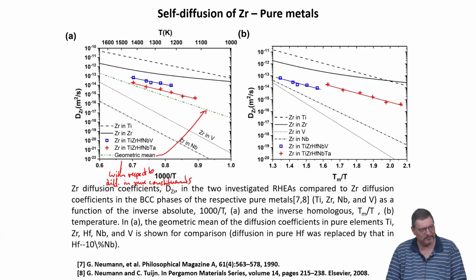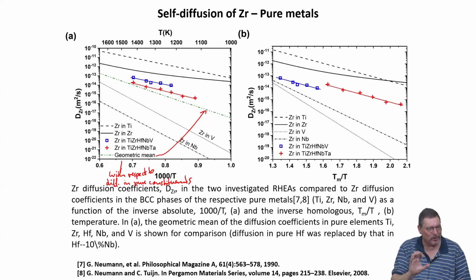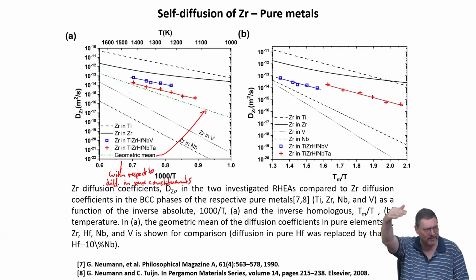What is your opinion? Diffusion is sluggish, or is it not sluggish? I think the good comparison is really given by this geometric mean. And this is basically showing it's not sluggish. It is actually a little bit faster as compared to what you expect as a reasonable comparison from the pure constituents. I would also not go as far as calling this anti-sluggish behavior, because it's just within the variational span we would expect going from pure constituent to a 5-component alloy. But certainly it is faster than you would expect if you do a simple calculation for the 5-component system, right?